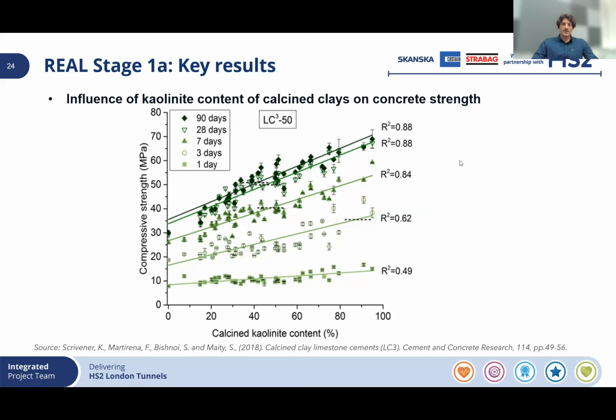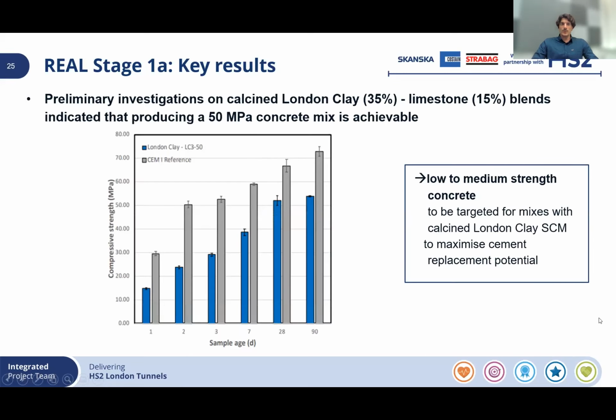Next slide, please. So this was what we did. Well, this was based on mortar samples with 35% London clay and 15% limestone, and the rest was Portland cement. And we found that we can reach up to 50 megapascals at 28 days for this particular test. So we thought, okay, that's promising. It's not high strength, so we can safely target low to medium strength concrete mixes. Next slide, please.